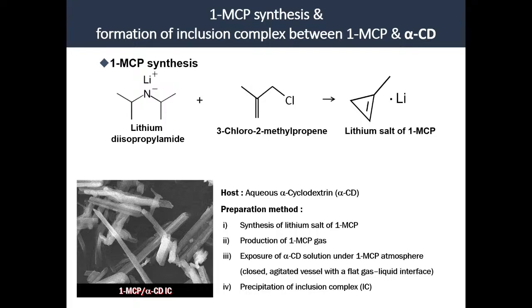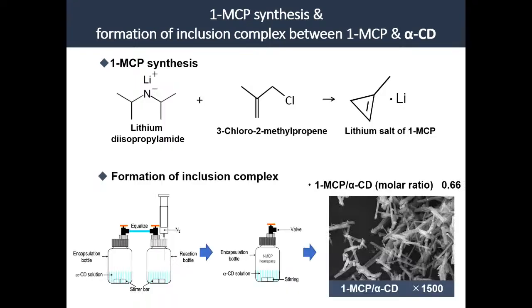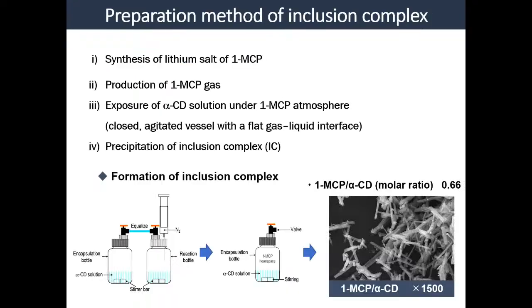So this is the formation of the lithium salt of 1-MCP. When we synthesize the 1-MCP powder, initially we need the lithium salt of 1-MCP, and then afterward we can get the crystal. So this is one experimental method, but...